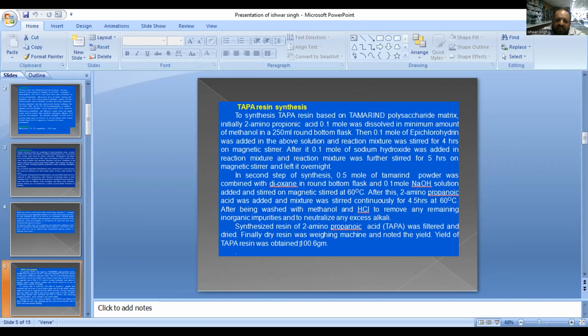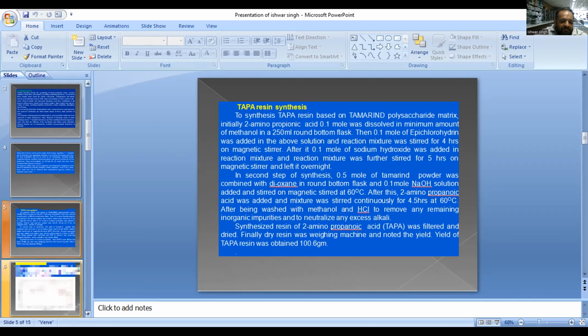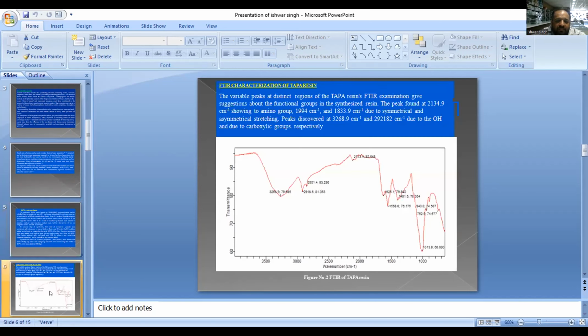And I found approximately 100.6 gram. The resin weight is approximately 100.6 gram, or we can say that it is the yield of the synthesis. Finally, I took the FTIR, and it is found near